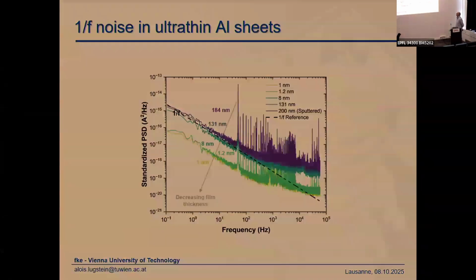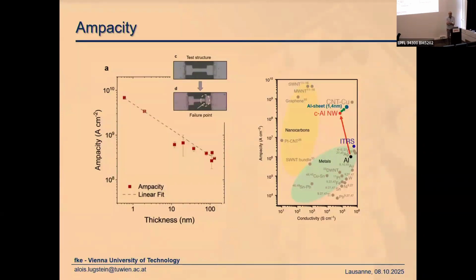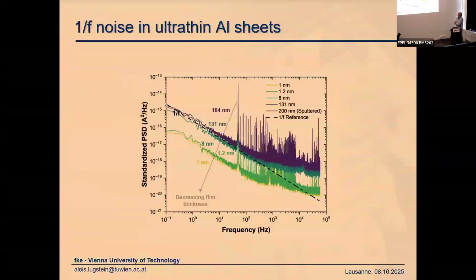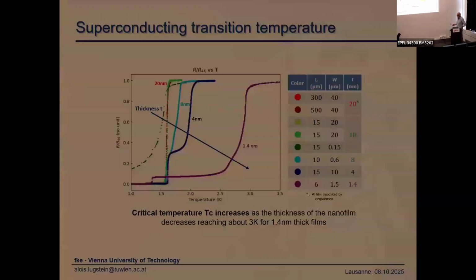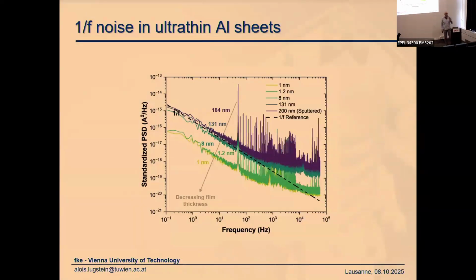So what we expect for these thin sheets is that we have a change in the transfer of the electrons through these sheets by a modified electron-phonon scattering, which is somehow proven by these very recent noise measurements. So you see that the 1/f noise decreases by about an order of magnitude when these layers get thinner and thinner. And the reason for that may be that these sheets are single crystalline. So in the common metallization scheme with aluminum, we have polycrystalline aluminum. You have this bamboo structure with grain boundaries, and these grain boundaries are mainly the reason for the failure.